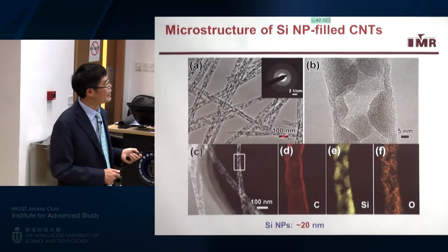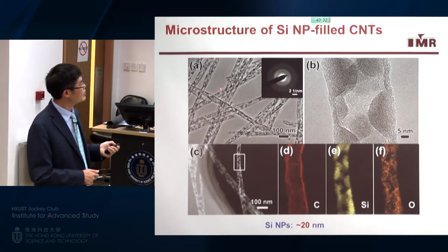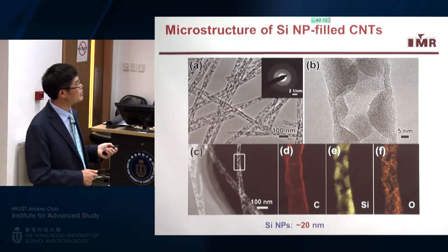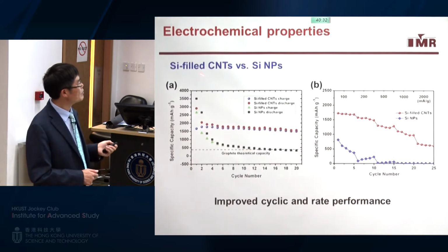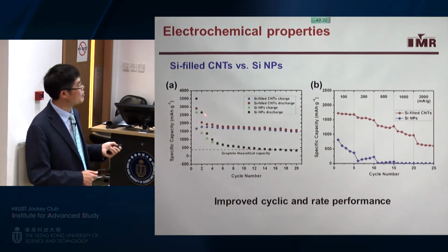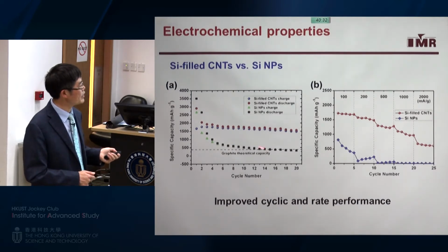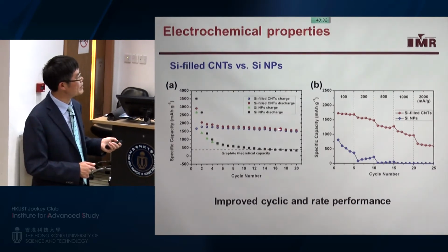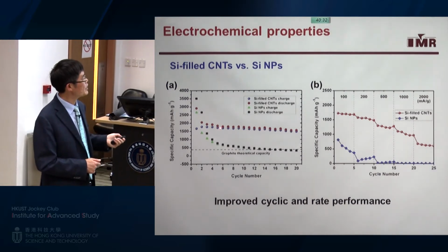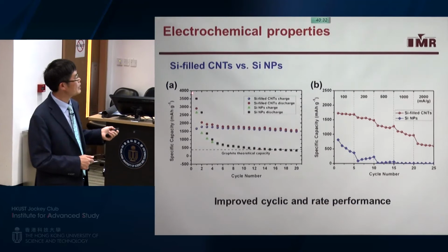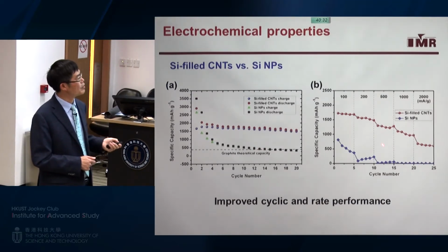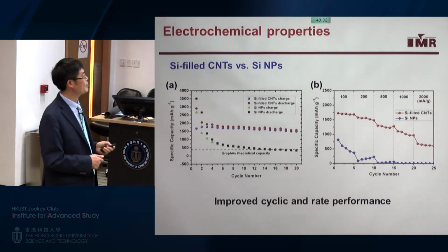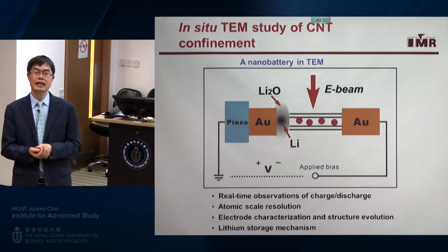Then we try to understand the mechanism. So this silicon nanoparticle is filled into the carbon nanotubes, and then we study the electrochemical performance. As I show here, this is pure silicon. This is the carbon nanotube confined silicon, which has a much better cyclability than the pure one, and also much better rate capability. You can see here this is the current density compared to this pure one. Then we try to understand the mechanism.